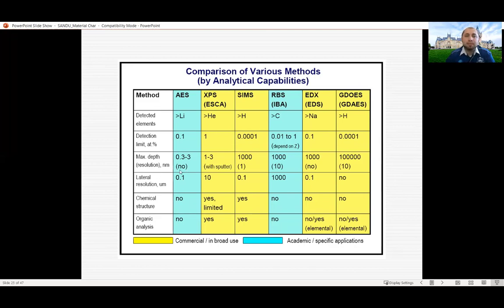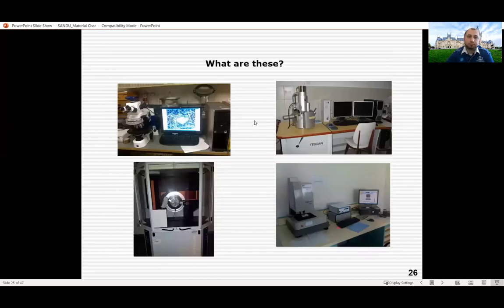and goes even higher for SIMS to 0.0001. Max depth resolution, you can see very thin from 0.3 nanometers up to 1 millimeter. We have also lateral resolution and many other characteristics. So depending on what kind of results we need to obtain, how in depth, then we have to select the proper technique that we have here on the table.